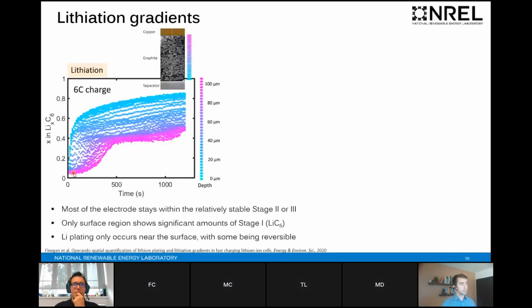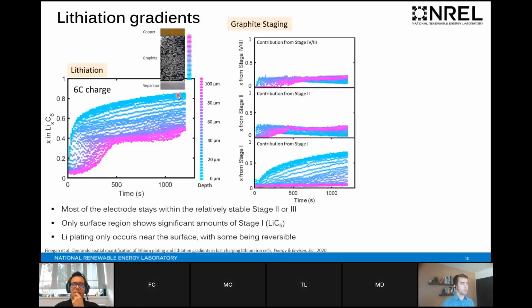And then over time, the region at the current collector starts to lithiate to a certain point, and the region close to the separator starts to slow down in lithiation as well. Now, because we conducted Rietveld refinement, we were able to look at the contribution of the individual stages to this overall lithiation state as a function of depth. And so we can see the response of graphite as it transitions from graphite to stage 3, to stage 2, or LiC12, to stage 1. And there are energy barriers associated with this crystal structure change in the graphite. The biggest energy barrier is the transition from stage 2 to stage 1. So the highest overpotential for lithiation is needed to make that transition happen from stage 2 to stage 1.